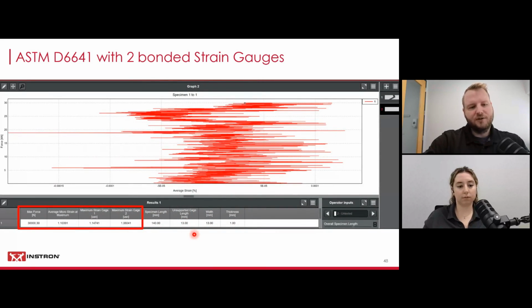And then I took this specimen up to 30 kilonewtons. Again, this is a unidirectional material. It's extremely stiff and therefore also shows very low strain readings. I was actually surprised how low those were, to be honest. I was hoping to be able to show you a little bit more. So maybe taking this all the way through failure we would see a little bit more.